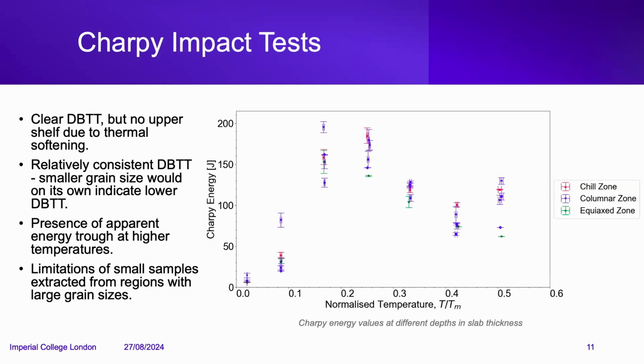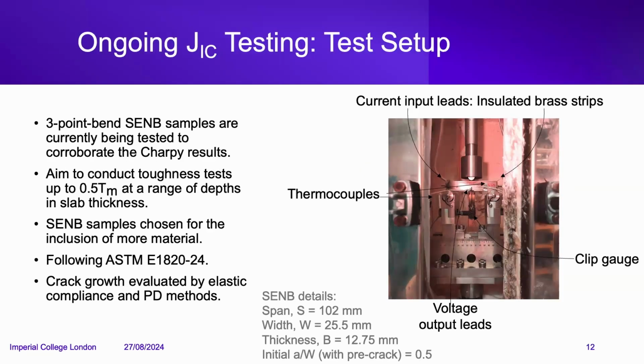But you can also see an apparent Charpy energy trough at about 0.4 normalized temperature here, which suggests perhaps there is a ductility trough effect here, lowering the toughness of the samples. But with Charpy samples, there is a lot of variability in measurements, so this does need to be corroborated, which is what I have set out to do. And so I do have some ongoing J_IC testing with 3-point bend SENB samples to test the temperature range up to half of the melting point of the steel as well, and to see whether or not there is actually a ductility trough present in the material.